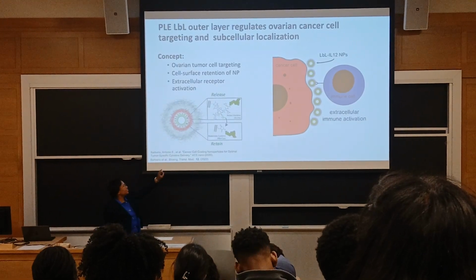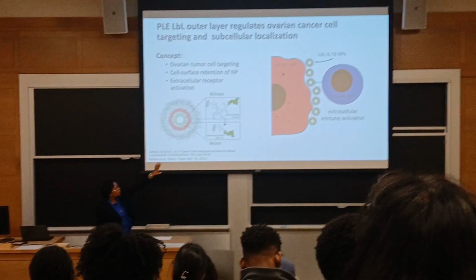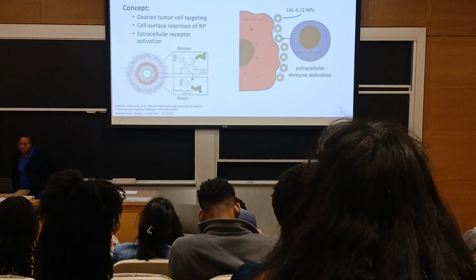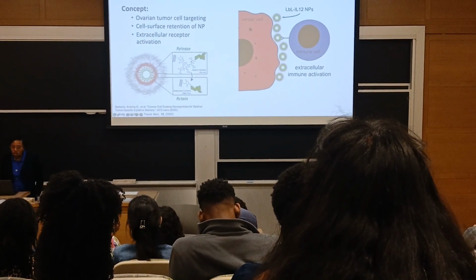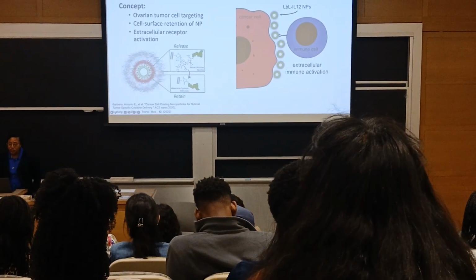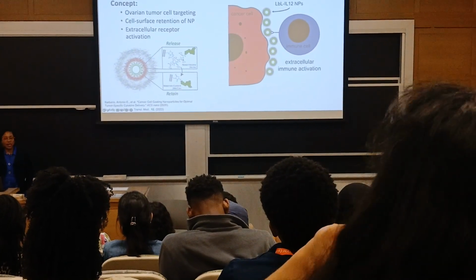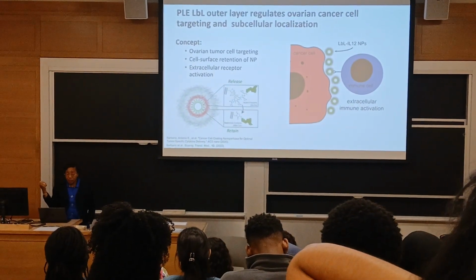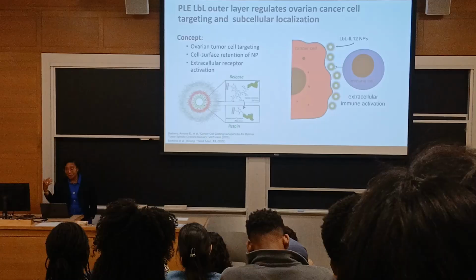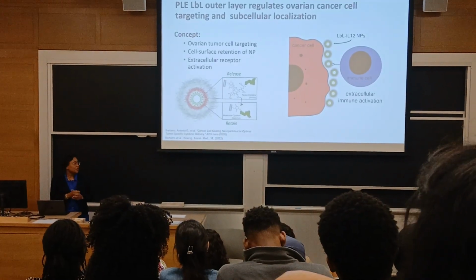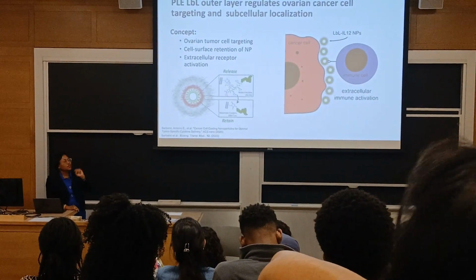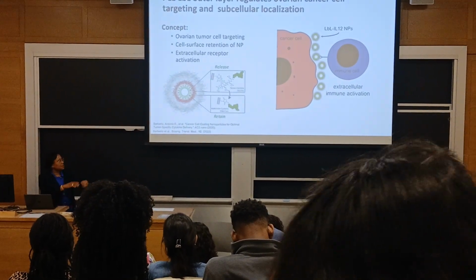So the conjugation that we first used was a nickel histidine. That basically uses the non-covalent interaction of nickel with histidine to get this protein anchored on. And it's used a lot in biochemistry as an easy tag. However, we can't take it in the clinic, but also it has some side effects. But also, it releases over a time period of about 24 hours. But we thought, let's start with this, and we'll release the IL-12 to the immune cell.